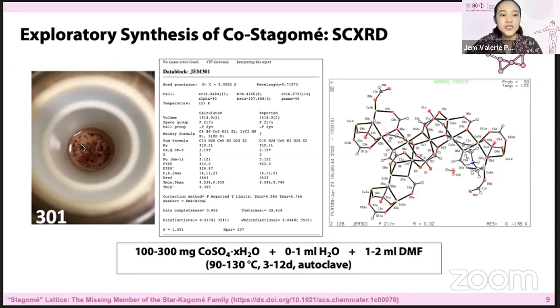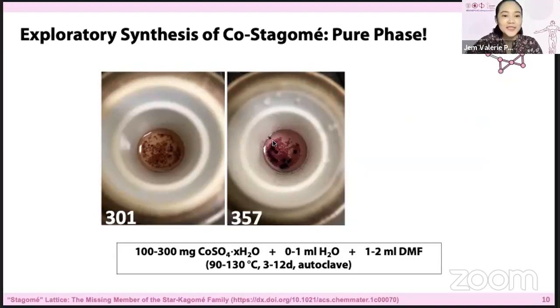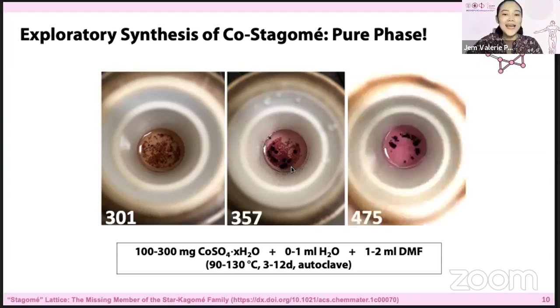So I played with different recipes or different parameters in the synthesis. And at the 301st reaction, after several more reactions, I was able to synthesize bigger crystals of the cobalt stagome compounds. And at my 475th reaction, I was able to synthesize all of it as the cobalt stagome compound and no more of the other known material. So I played around with this recipe: the cobalt sulfate, water, and DMF concentration or amount ratio, and the temperature and the time of the reaction. Having knowledge of the kinetics and thermodynamics of these reactions, I was able to synthesize the pure phase